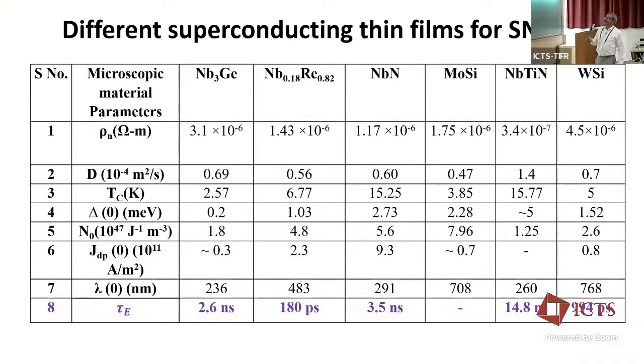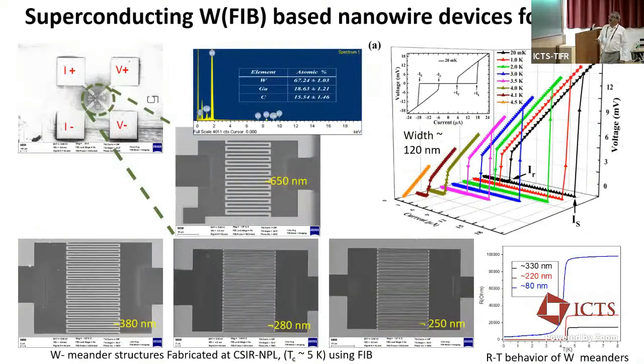So this is work being done at NPL. We have optimized the thickness of few nanometer thick superconducting thin films. These are the different materials which we are working on. And we use an FIB or electron beam lithography at IIT Delhi to make these meander structures. So these nanowires are used for SNSPD devices. We optimized these device structures, and then measured the light response from these structures.